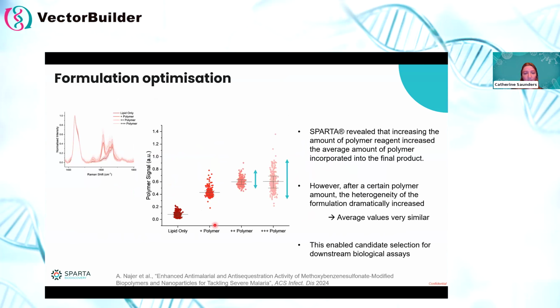You'll see on the x-axis here there are these 4 samples. There's one with no polymer, lipid only, and then increasing initial amounts of polymer that was added. What you'll see is that as we increase this polymer amount, the amount of polymer incorporated is increasing up until a saturation point. So for this, I can just look at these mean lines.